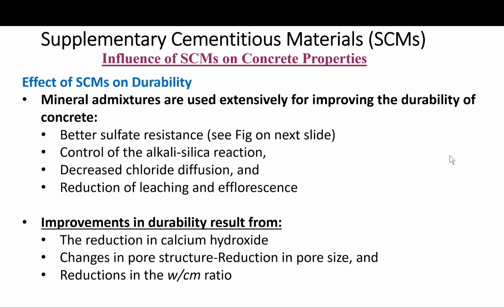Also, the calcium silicate hydrate formed in the pozzolanic reaction can absorb alkali ions to a greater extent than that formed by the hydration of the calcium silicates alone. So admixtures with high alkali contents may be less effective in this case.